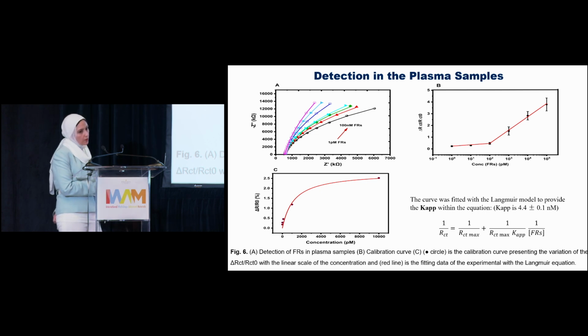We prepared our human serum plasma and spiked it with our folate receptor protein in a wide linear range from 1 picomolar to 100 nanomolar. As we see, there is an increase in the semicircle diameter with increasing concentration of folate receptors. We made fitting for all the data, extracted the value of RCT, and calculated the variation of RCT to plot against the logarithmic concentration of the protein, to obtain our limit of detection from the calibration curve.